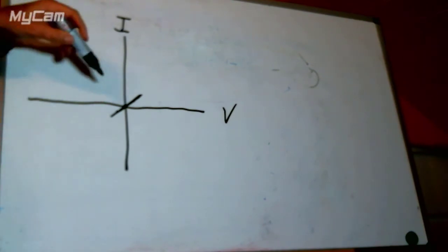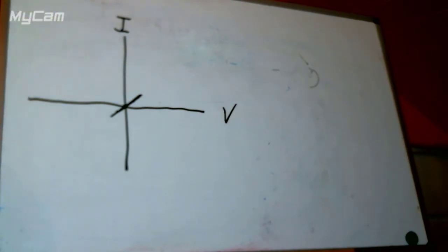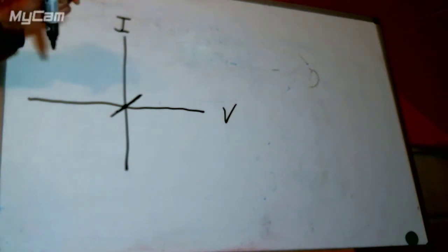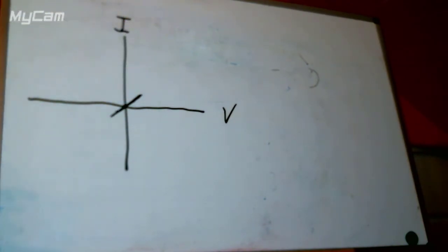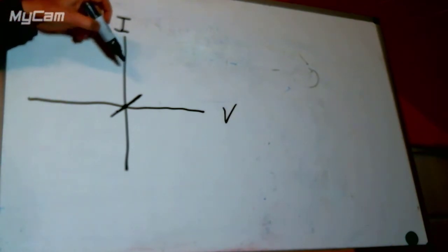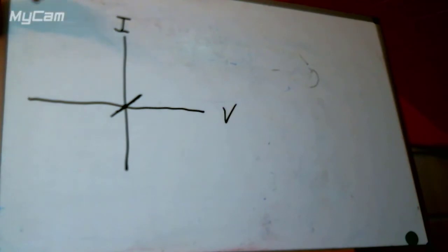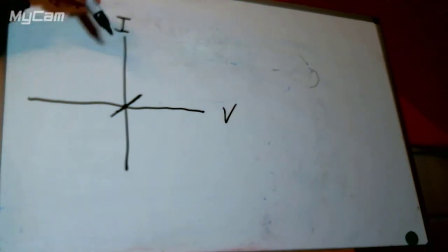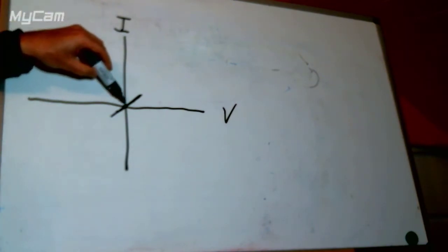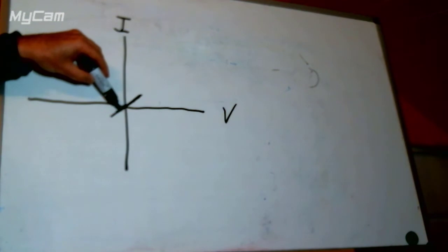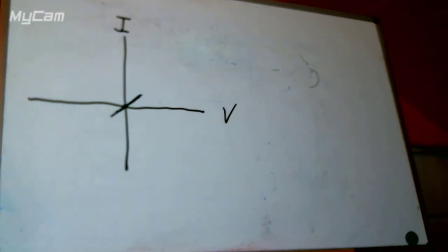And there's no logical reason why it should be different below and above the 0 line for this particular example. In this particular example, we've got copper in solution already, and we've got copper as our electrode. We've got a bare copper surface, and we have a dynamic equilibrium at 0, so it's going in both directions, so we can just push it a little bit in one direction and a little bit in the other direction.